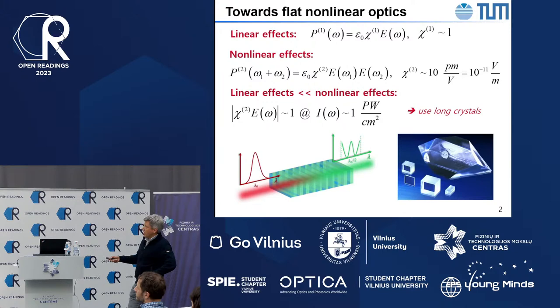So in order for you to build a similar concept, flat nonlinear optics, that is, nonlinear optics which produces a significant amount of, say, difference frequency generation from atomically flat layers, you need the nonlinear polarization, P2, to be comparable in strength to the linear polarization components, because we know in linear optics it works, so nonlinear optics has to be of the same order. Now, you could look at the values of chi2 and realize that in order for these nonlinear effects to be comparable to the linear effects, you need the electric field strength such that the product of chi2 times the electric field gives you something of the order of 1. Then this term is comparable to that term.